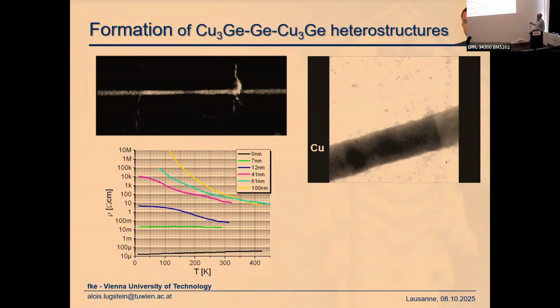And you can control the length of your device without any expensive lithography, just by controlling the annealing temperature or annealing duration. And with that, you can make ultra-scale devices. What is shown here is the length of the remaining part of the germanium nanowire. So you can make a device with a segment length of 100 nanometers, 61, and down to 7 nanometers.